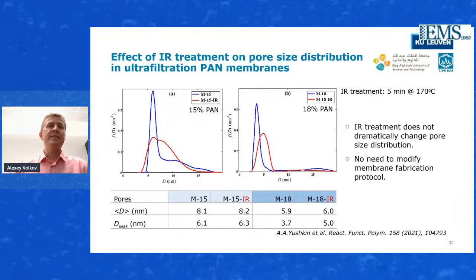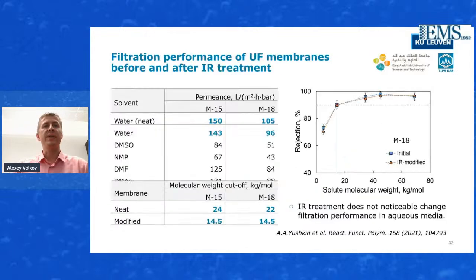And as I said, we didn't find any change in the morphology and also not so much change in the pore size distribution. So it means, once again, that we don't need to modify the membrane fabrication protocol. We take the membrane as it is, we make a post-treatment that turns the membrane from soluble to insoluble form. And then we can use that for the filtration of different organic solvents, or to use it as a support for the casting of a thin film on top of that.